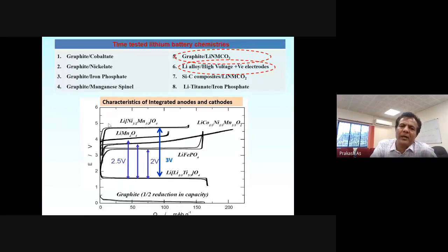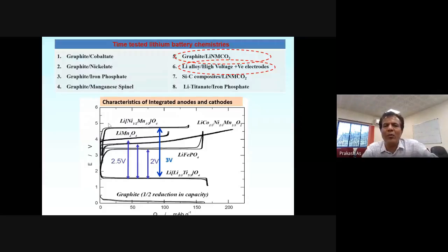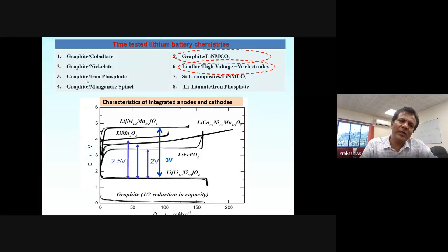Now, as I said, a lithium battery is a combination of a positive and a negative electrode, right? As I said, an anode and a cathode. Cathode is the positive electrode, anode is the negative electrode. If you look at the industry, several types of chemistries exist. You can use graphite in combination with lithium cobalt oxide, graphite with lithium nickel cobalt oxide, graphite with lithium iron phosphate, graphite with lithium manganese oxide, graphite with NMC, or alloy-based electrodes with the positive electrode, or silicon carbon composite. So there are several compositions.